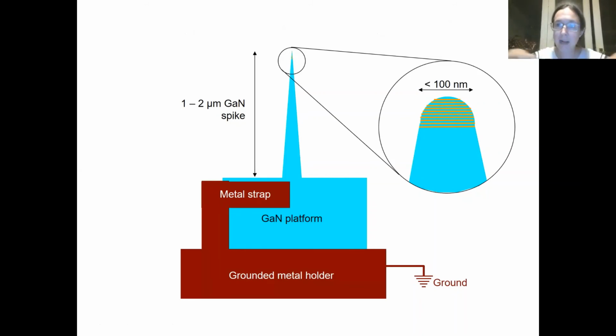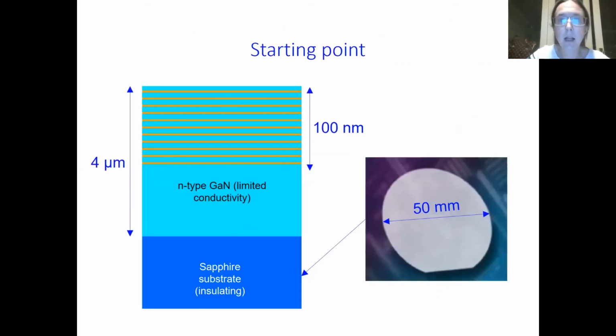To do that, we have to take a gallium nitride device, which comes from what I would call a wafer, a kind of flat plate of the gallium nitride crystal. We need to make a 100 nanometer needle, and it needs to be possible to apply an electric field to it because otherwise we can't apply our bias and get our field evaporation going. So we need a 1 or 2 micrometer long gallium nitride needle with, at the very apex, a region with the quantum wells in that's about 100 nanometers across. That is not a very easy thing to make.